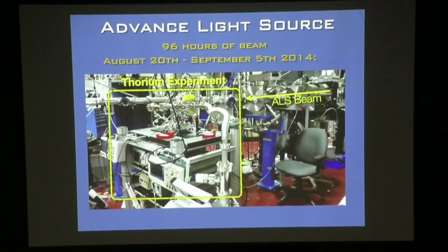I will tell this story, actually, because maybe somebody's here, and it will do some good. When we got this run here, we didn't know if the crystals were going to survive or not. They were the first real batch of radioactive crystals, and we didn't know if they would just decompose in a day or a couple of weeks. So they basically come out of the oven, they're polished almost while they're still hot, drop them in the envelope, and ship them to the ALS. We also brought a thorium-232 crystal to the ALS. So thorium-232 is the regular thorium. It doesn't have this nuclear transition. And the idea was this was our control crystal: if we see something in the 229 crystal, we'll drop in the 232 and it should go away.